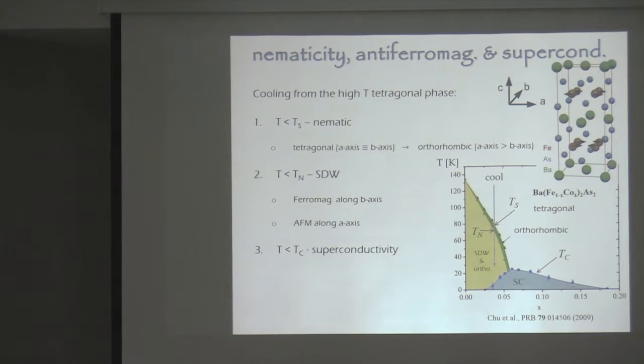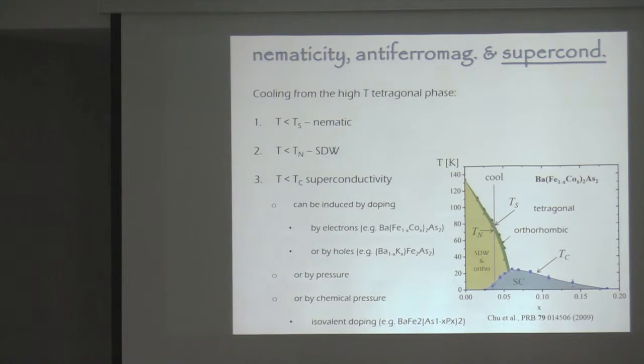But basically, when you cool your sample, it first undergoes a nematic phase transition from tetragonal to orthorhombic, and then it goes through a spin density wave transition to a spin density wave state, and these states are very closely associated with one another. They almost always come together. And then if you cool more, you get to the superconducting phase. So here's the superconducting phase. This phase diagram has doping and temperature.